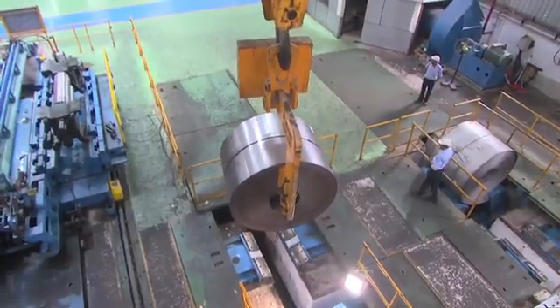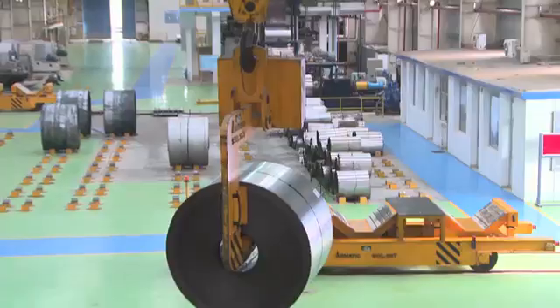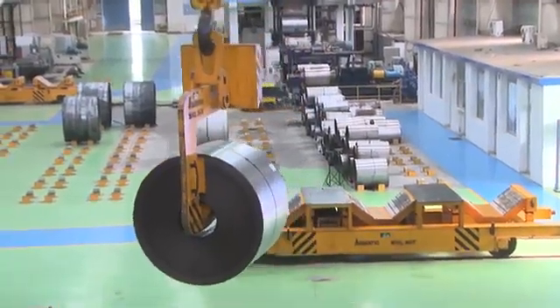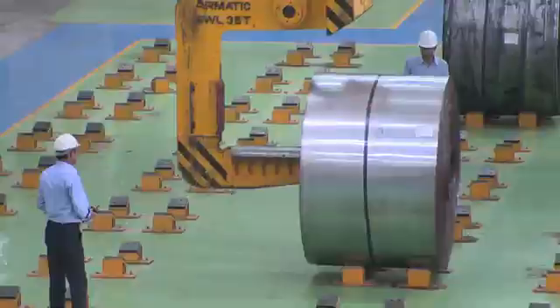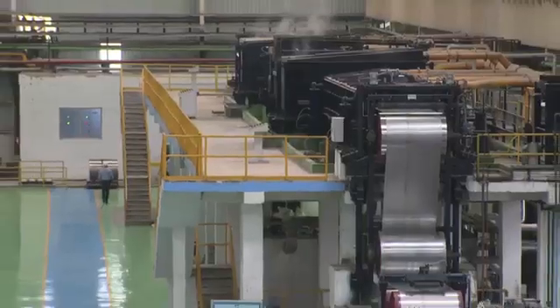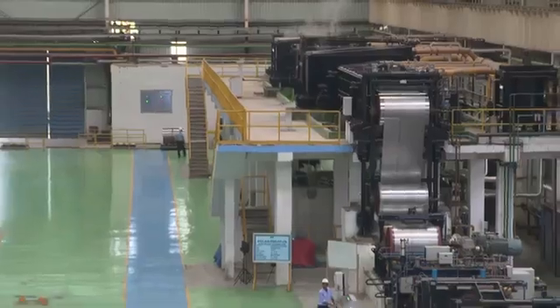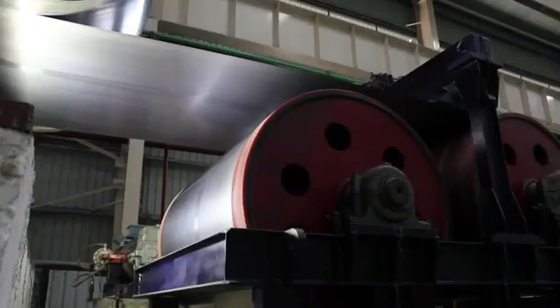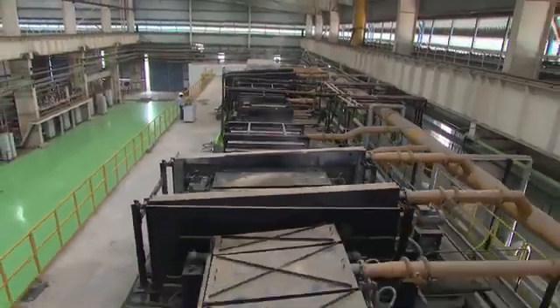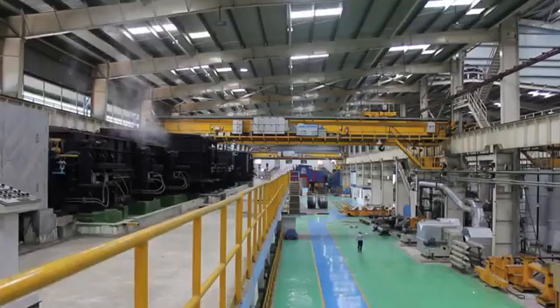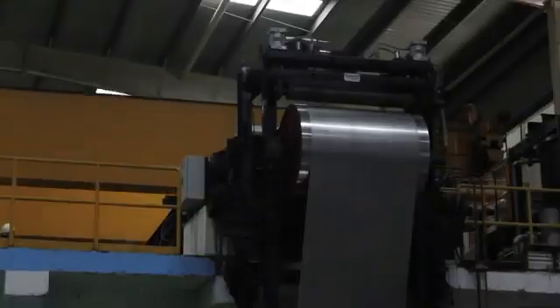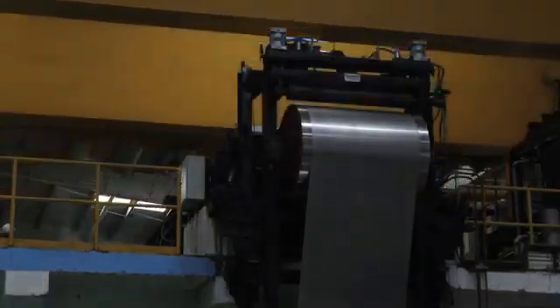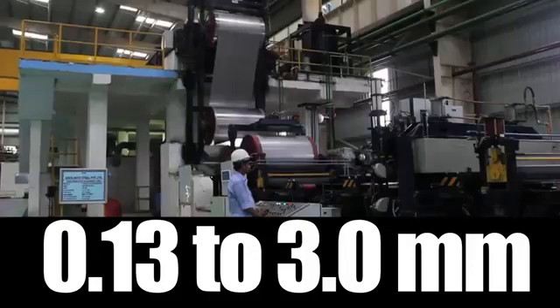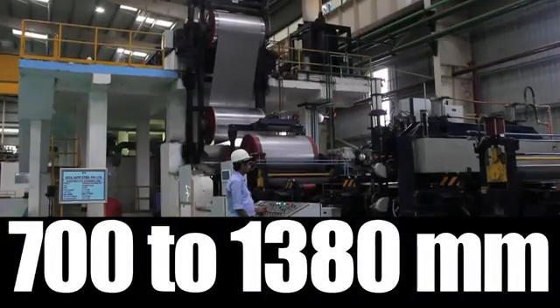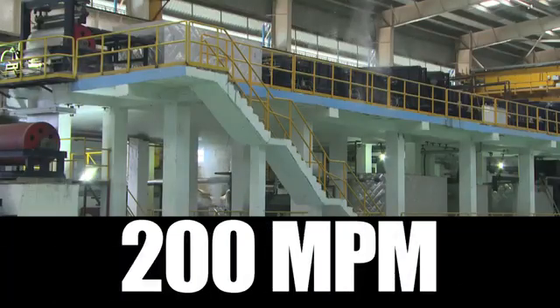Once the coil is rolled on the cold 6HI rolling mill, it is transferred to the electrolytic cleaning line through EOT cranes. Electrolytic cleaning line from SMS Siemag Group, the ECL. The residual oils and iron fines present on the cold rolled strips are removed through an electrochemical process. This equipment has been designed to handle strip thickness from 0.13 to 3 mm, width from 700 to 1380 mm, with a max speed of 200 meters per minute.